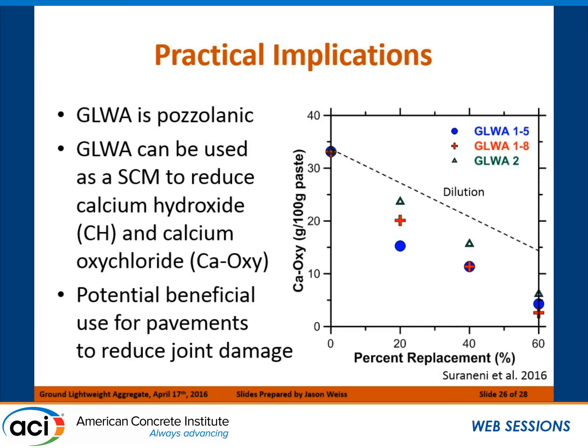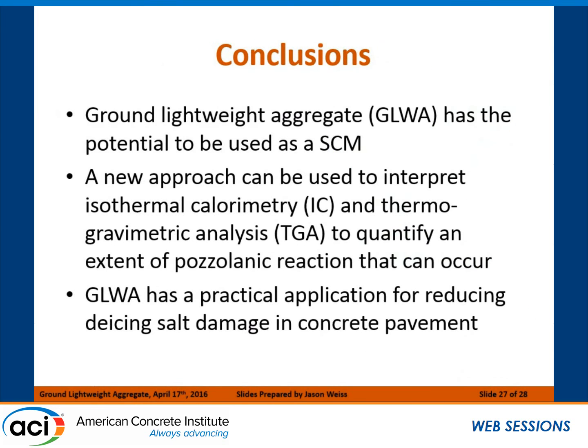So one of the big questions is the age-old question of how low can you go, or how low do you need to go, where this doesn't become a big problem. Right now we're saying around 10 seems to be a good number, what people are seeing in the field where they're not having problems. But this is something we really need to continue working on to see where that number needs to be. What we do know now is that the addition of SCMs, fly ash, silica fume, ground lightweight aggregate, anything else that's going to react there to consume the calcium hydroxide is good at minimizing this joint damage.